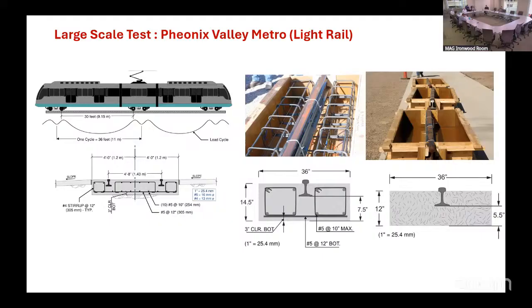Original thickness was 14.5, and they challenged us to go to 12 inches. So that's about 2.5 inches, about 20% thinner, but take all of the rebar out that is there. So that is the idea that we made about 6 different samples. Standard reinforced concrete, the way it is shown on the left picture, and then just set up the rail and then put in the steel fibers or polymeric fibers or different types. So that was the whole challenge.